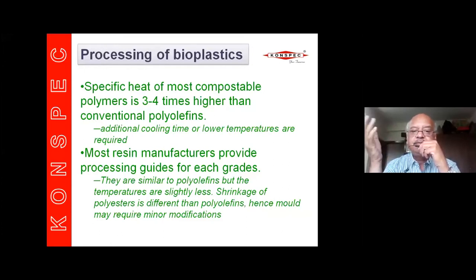Now, most resin manufacturers provide processing guides for different grades, but I will just tell you that the processing is similar to that of polyolefins, except that the precautions I mentioned earlier are taken. The temperatures involved are slightly less, 10 to 20 degrees less, and material can be processed just like any other conventional polymer. It is nothing very different, or no separate skill set is required except some precautions. Another thing is shrinkage of these polyesters is very, very less. So PLA will shrink a lot less than standard PP.